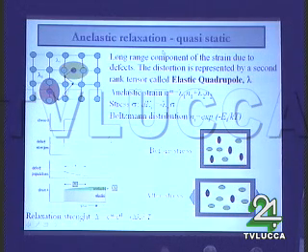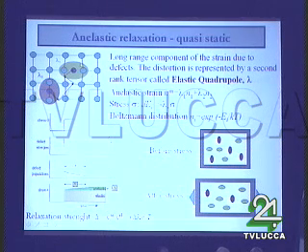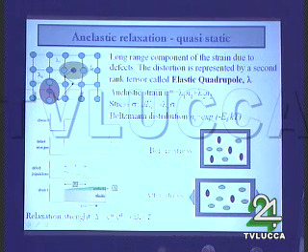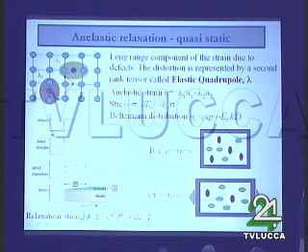I must spend just a couple of words to illustrate what anelastic spectroscopy is. Any point defect introduces a lattice distortion represented by a second-rank tensor called elastic quadrupole. The distortions can have different orientations within the lattice, but they are energetically equivalent in the unstrained and unstressed sample.